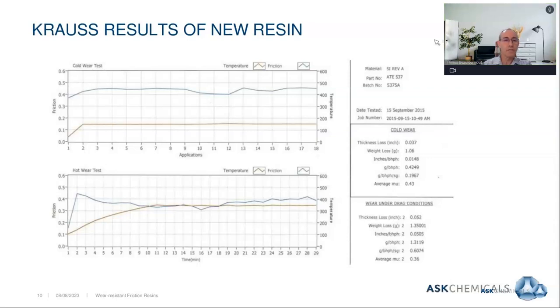This next slide then shows the Krauss results of the new technology. And immediately you can see that at the 150 degrees Celsius test, the friction coefficient is quite stable in the initial applications. Slight green fade again, and good recovery. We compare that to the results at 350 degrees Celsius, where the friction coefficient shows a slight initial green fade with a good recovery, and this recovery is well within the 10% tolerance of the 150 degrees Celsius test, which is, if you interpret it that way, a very good or desirable behavior.